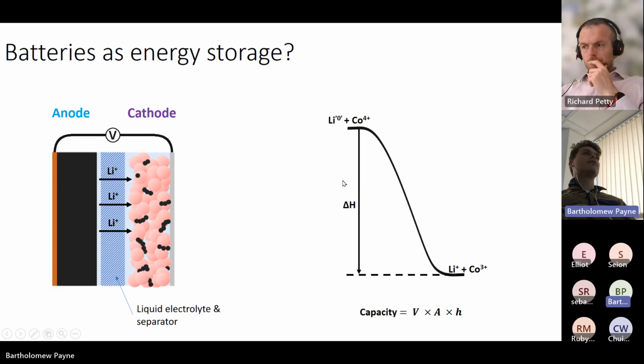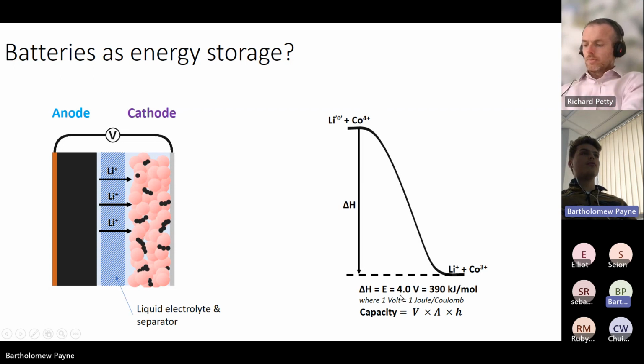And if we think about that potential energy landscape, you start off in your charged state up here. Once you've charged the battery, you've got your lithium almost in its metal form, in its Li0 oxidation state, and then your cobalt 4+. Then you've got this difference in energy between these starting materials and these products here. This is when you fully discharge the cell, and the actual energy difference here is 4 volts, which is a lot more than anything we saw before. So each electron which moves through this circuit is going to do 4 volts of electrical work to power all the components in your circuit, which is why it's so important for the modern life we live, where everything is electronic and powered by electrical energy.